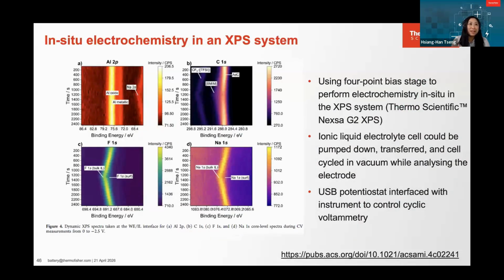Here are the figures. They were actually spectra collected during the entire cyclic voltammetry experiment. The figures show here what corresponds to the peak maximum, and they were plotted as a function of experiment time, again reflecting the sweeping voltage that is being used during the experiment.